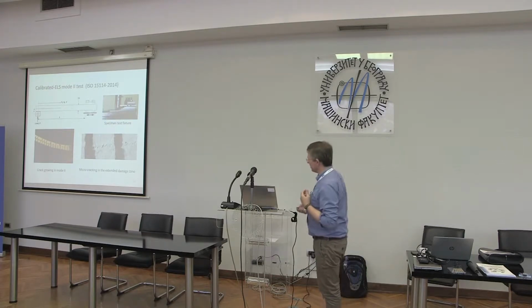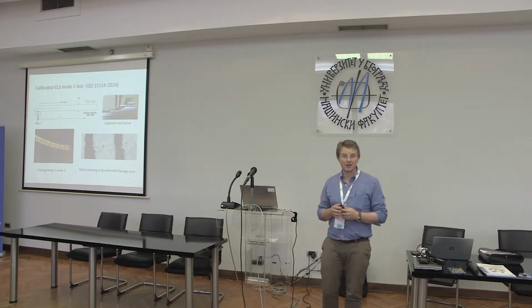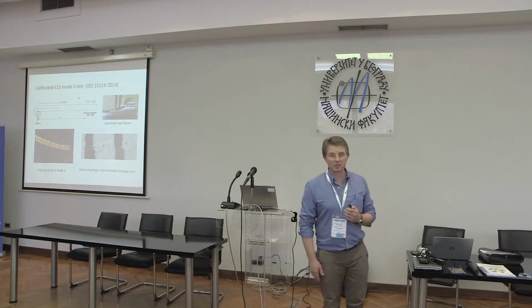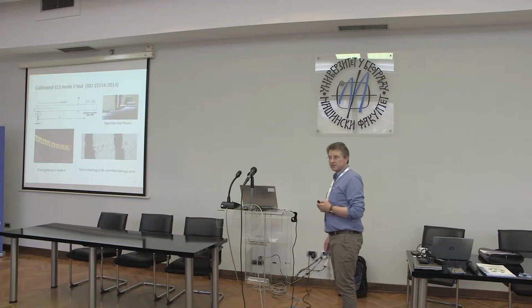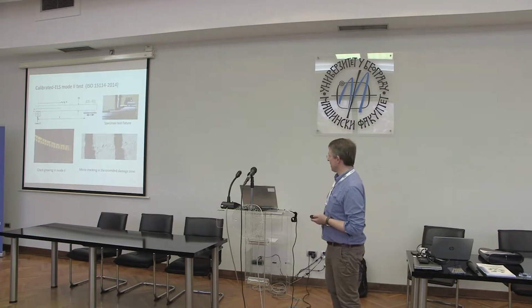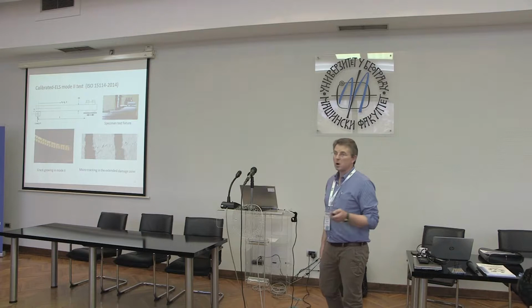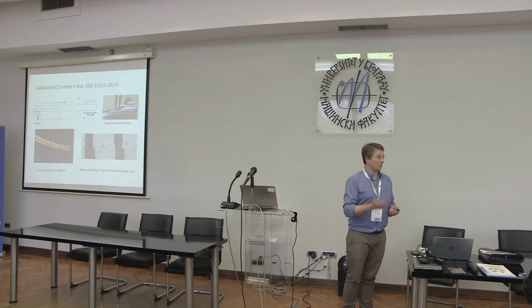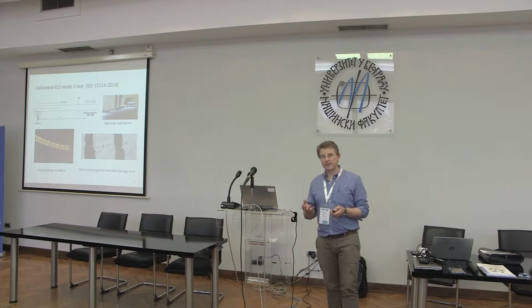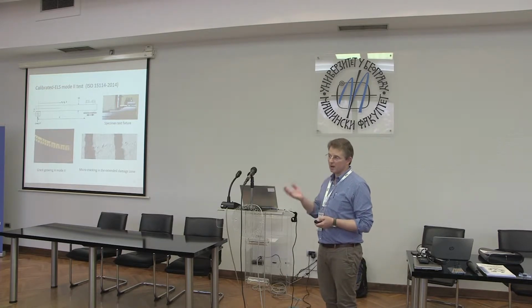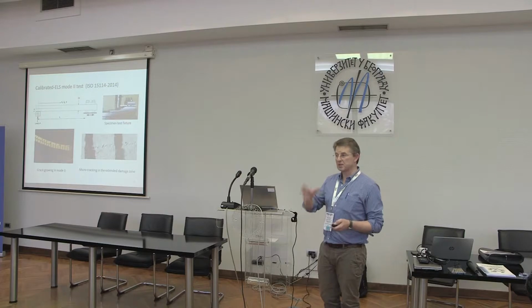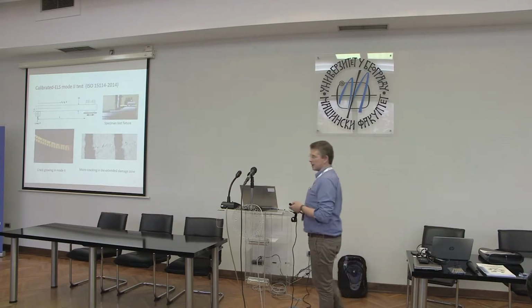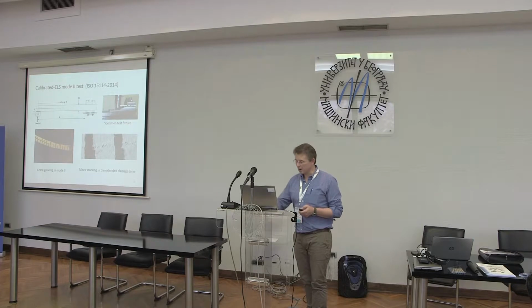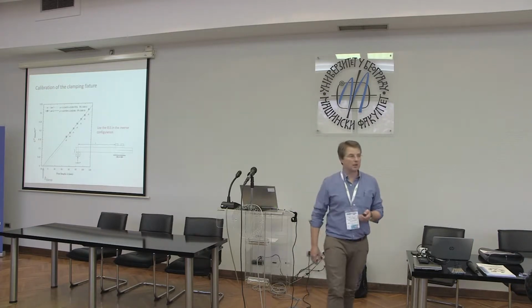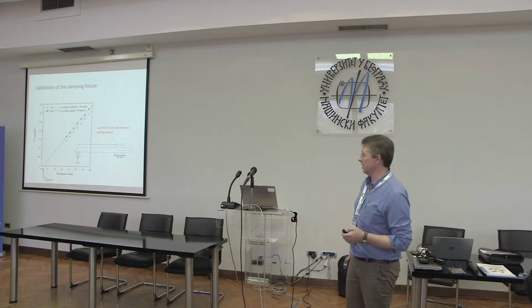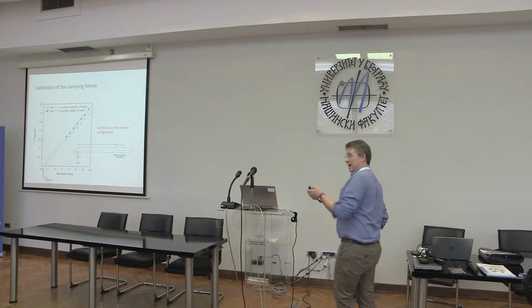So what we decided to do was to abandon the whole concept of measuring crack length in these experiments and move to a compliance-based way of approaching this. And of course, if you base crack length from compliance, basically what you're saying is you're going to measure an effective crack length based upon the compliance of the specimen, based upon, for example, your corrected beam theory. So you would assume a particular theory, and then you're going to apply the compliance theory to that, and we're going to take out the crack length.